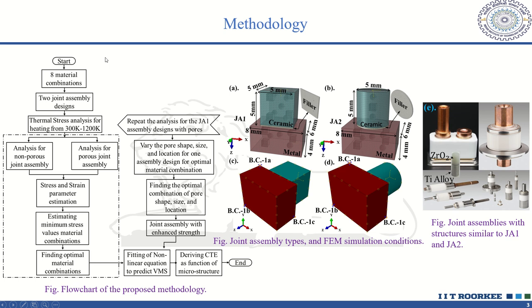So, in this study, 8 material combinations are tested with two joint assembly designs JA1 and JA2. The thermal stress analysis is performed for heating these joint assemblies from 300 Kelvin to 1200 Kelvin. The analysis is performed for both porous and non-porous joint assemblies, and then stress and strain parameters are estimated and the optimal material combination corresponding to minimum stress value is estimated.